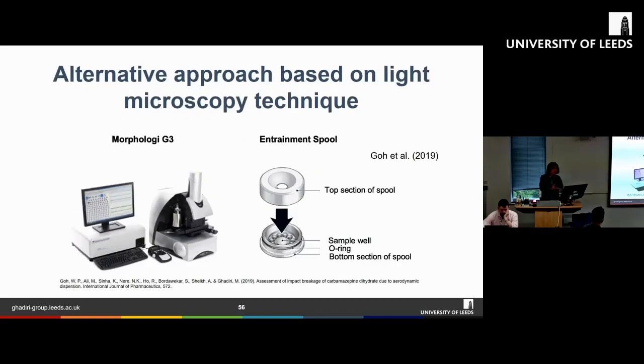So we use a different approach instead. Instead of using laser diffraction, we move on to using a light microscopy technique, in which we actually see the particles. So we actually look at how the particle breaks. For laser diffraction, we are using the scattering of light, so we don't really see how the particle breaks. But with a light microscopy technique, we can do that. We can actually assess how needle-shaped particles break.